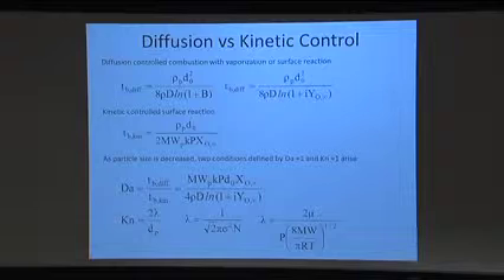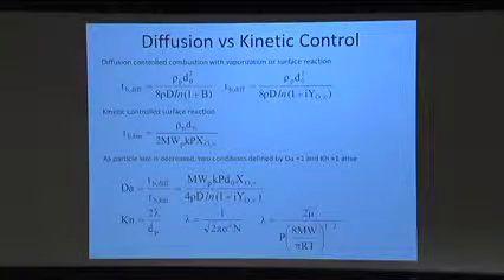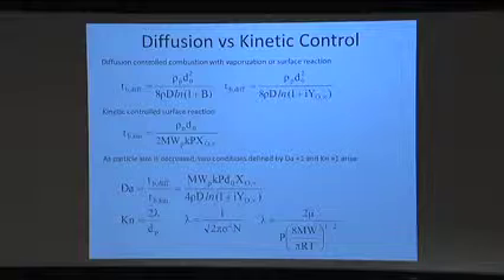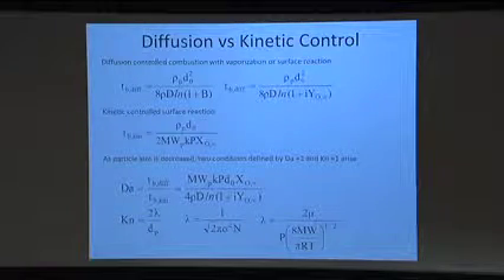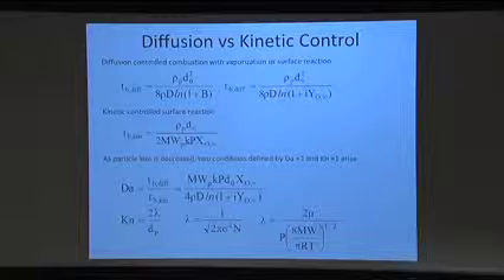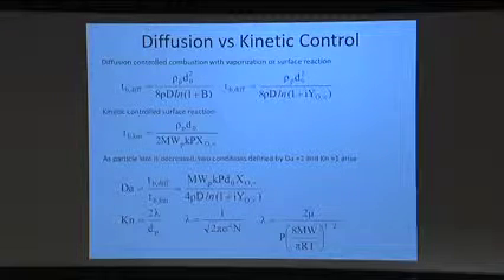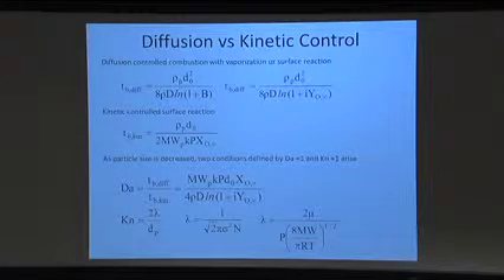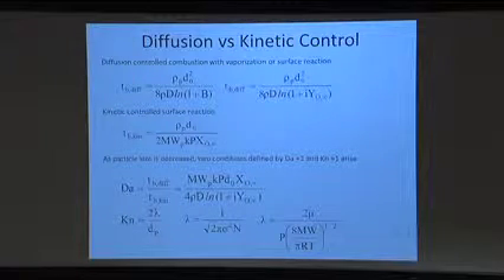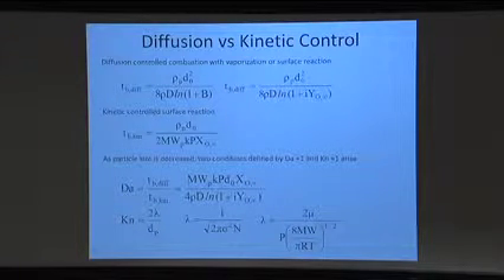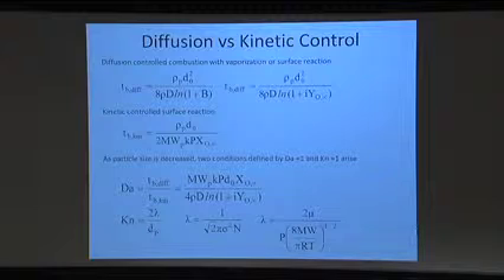Now, if I ask the question, well, what's going to govern when these two processes change from one to the other, I might define some sort of Damkohler number where I look at basically a characteristic diffusion time to a characteristic kinetic time and just take the ratio of these two terms. And I took these terms here. And if you do that, you get an expression like this. Okay? And what this tells me then is if I'm looking at large diameters or very high pressures, I'm going to basically have a diffusion controlled situation. If I'm looking at very small diameters or low pressures, then I'm going to have basically a kinetic controlled situation.